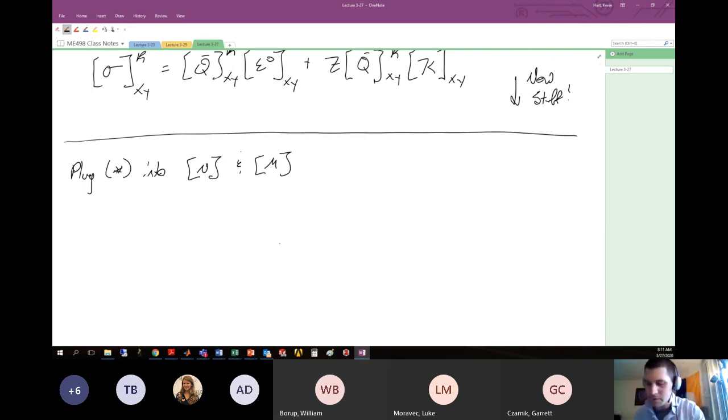Remember last time also we discretized some of those integrals to help ourselves talk about the stress distributions in each one of the individual layers. And so ultimately, if we plug star into these relationships for the forces, we could come up with something like the vector n in the xy coordinate system. Here, remember this is 3 by 1, equal to the summation from k equals 1 to n. So we're summing over all of the individual lamina layers in the laminate.